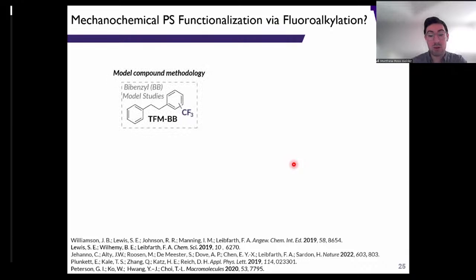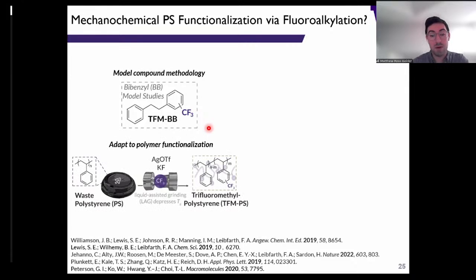So what we were after here was thinking about some type of mechanochemical post-polymerization modification approach that we could study not only on a small molecule model of polystyrene, such as bibenzyl, but then eventually apply to waste polystyrene. The specific method that we're after here is trifluoromethylation. And that's not because that trifluoromethylated polystyrene is the most useful material out there, but it really gives us a handle via 19F NMR spectroscopy for quantifying the amount of functionalization.